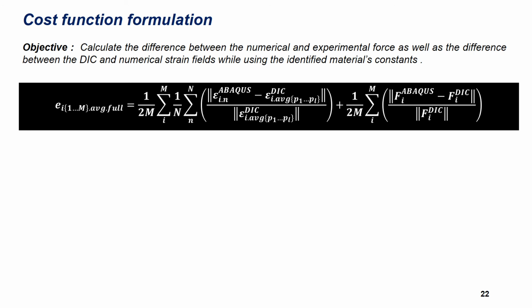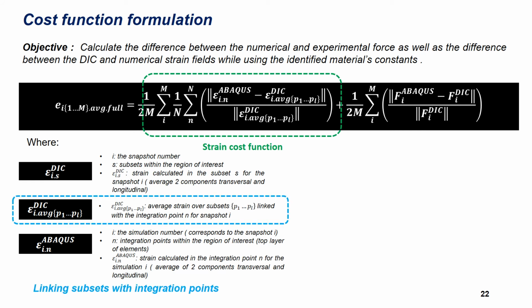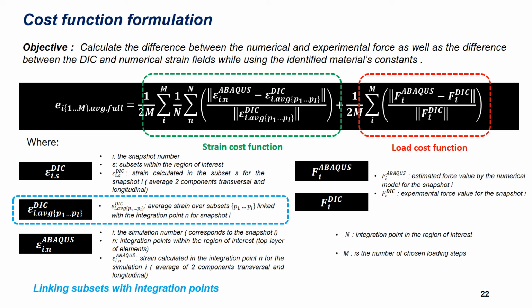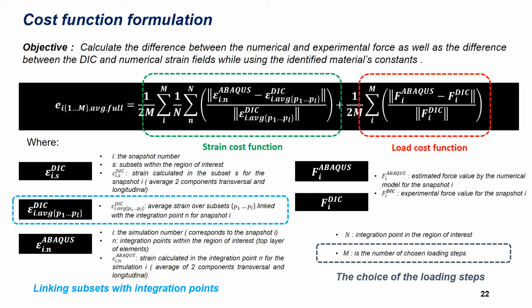The objective is to calculate the difference between the numerical and experimental force, as well as the difference between the experimental strain field and the numerical strain field, using the previously identified material constants. For that, a cost function was defined and can be decomposed into a strain cost function that compares data between integration points and the subset from a snapshot, and the load cost function, which compares the experimental load and the numerical load. We also decided to evaluate the cost function on different loading steps.